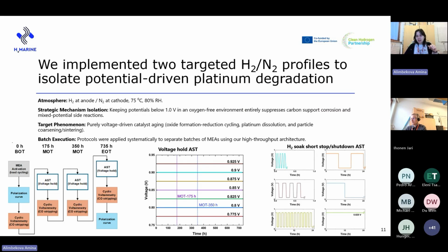As discussed, the real world maritime duty cycles are quite complex and they introduce multi-stress degradation environments. But to isolate the pure platinum catalyst degradation from overlapping issues like carbon support corrosion, we have decided to use the hydrogen-nitrogen environment and remove completely oxygen from the cathode and maintain the potentials at values below 1 volt. We can suppress carbon corrosion.